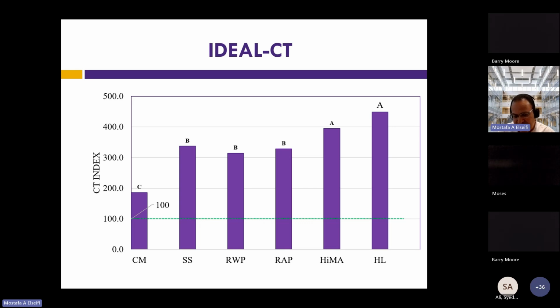So what we did here is different: we did not grind the plastic, we used it to replace part of the aggregate, so it was actually a larger piece. We determined the particle size of the plastic, then we removed aggregate of the same size and replaced it with plastic. In that case, we don't affect the binder in any way. We found some benefit in doing that. I know that you guys are doing a lot of work in plastic, and that's something you may consider: instead of grinding your plastic, consider adding it as a replacement for the dry aggregate. That will allow you to use more plastic in your mix. In my opinion, that's exactly what we are trying to do. We are trying to address the landfilling of waste plastic by using it in the mix. So if you can use more, it will help us address this issue.